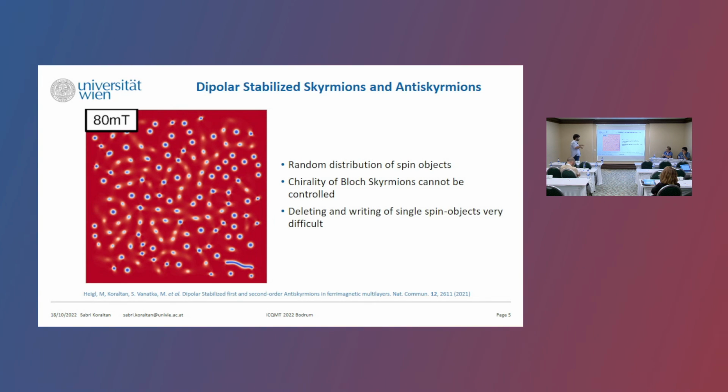You use the vortex to nucleate it at a certain location, but when you move it out, you are basically in this system where you do not have any vortex on top. But in this system, it's also stable. In artificial skyrmion lattices, they use this 1 nanometer PMA layer, which cannot host the skyrmions outside of the vortex. So it's just an imprint of the exchange interaction, basically. But in our system, you go out and you're in the skyrmionic system where you can have skyrmions all the time.